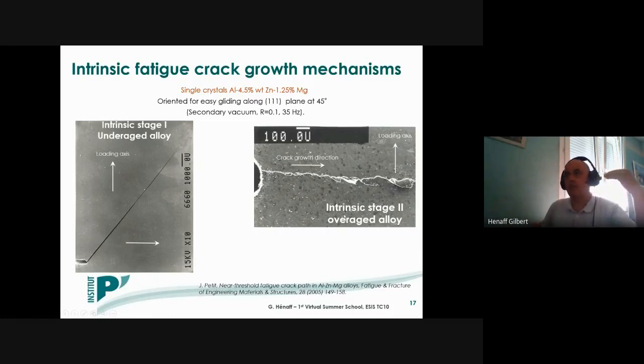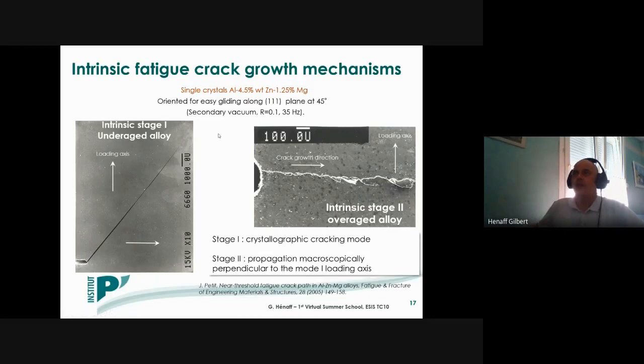So this is what we will call the intrinsic stage 2 propagation, while here in the case of the underaged alloy, you can see that again, here you have the notch, and you have an extremely straight crack path with a crack propagating within the slip system, which is activated during the cyclic loading. And so this will represent what we will call the intrinsic stage 1 propagation. So the stage 1 is a crystallographic cracking mode or slip band cracking mode. And the stage 2 is characterized by propagation, which is macroscopically perpendicular to the mode 1 loading axis.